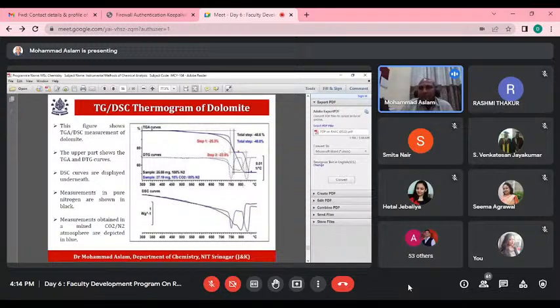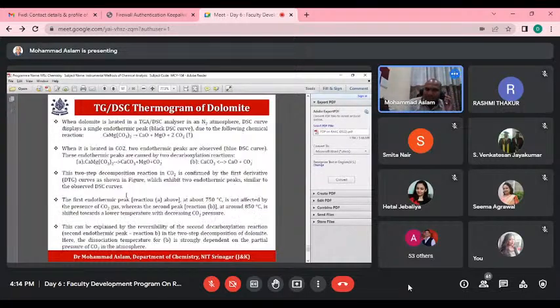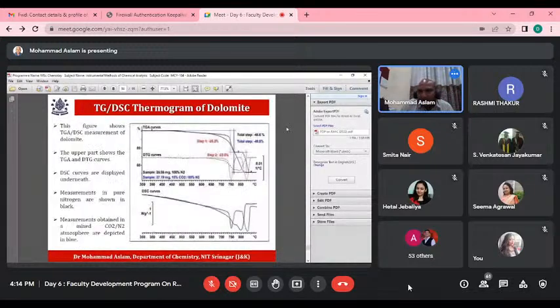If you go for this analysis, the DSC curve shows one endothermic peak in one case, and in the other case there are two endothermic peaks. I will discuss the significance of this. When dolomite is heated in the nitrogen environment, DSC displays a single peak. In nitrogen, that is the black one, it is a single peak. When we go for the CO2 environment, then two peaks.